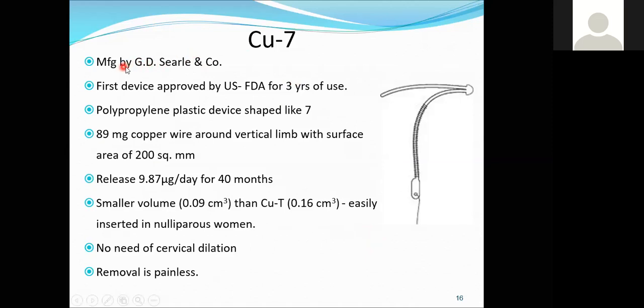Some of the products were manufactured by GD Searle and Company. Copper 7 was first developed and approved by the US FDA for 3 years of use, a polypropylene plastic device shaped like a 7. 89 milligrams of copper wire were wound around the vertical limb with a surface area of 200 square mm, which releases 9.87 micrograms per day for 40 months. Its smaller volume, 0.09 cubic centimeter compared to 0.16 cubic centimeter for the CuT, means it is easily inserted into nulliparous women. There is no need for cervical dilation, and removal is also painless.